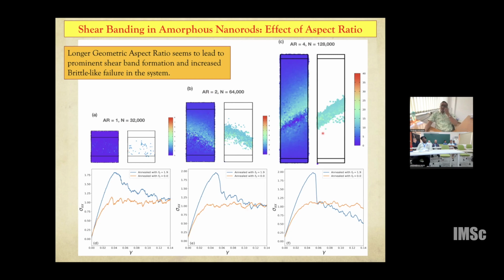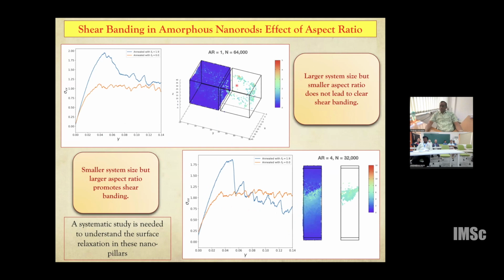It suggests that along with the annealing protocol, as you go to an open geometry scenario, your sample geometry is going to start to matter for stability. To stress the geometry, we looked not at the sample size. We looked at a bigger system, 64,000 particles, but in a cubic shape, and you see there is no shear band. But if you take a smaller system of 32,000 particles with an aspect ratio of 4, then you get a very clean shear band. So with a smaller aspect ratio you get less shear band formation, but a smaller sample with an elongated geometry will have much more shear banding.